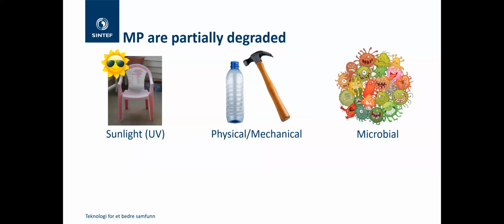The primary one is actually UV degradation, because this really changes the properties of the material. When you combine UV with something like physical or mechanical degradation, that could be wave action, it can be all sorts of different things, then you start to get this fragmentation process. You hear a lot about biodegradation and microbial degradation, but for all of the conventional thermoplastics, the understanding is that no microbial degradation is going to proceed until you get down to the molecular level. So you've got to have a lot of other degradation mechanisms occurring first.